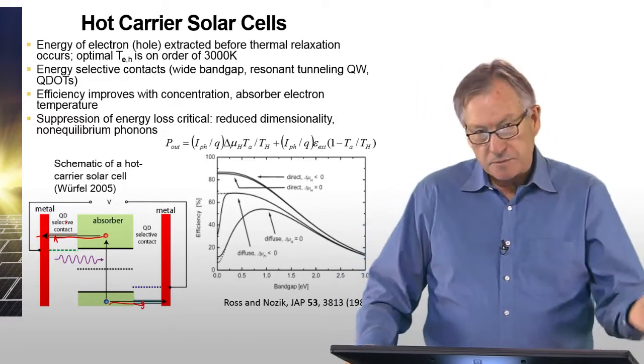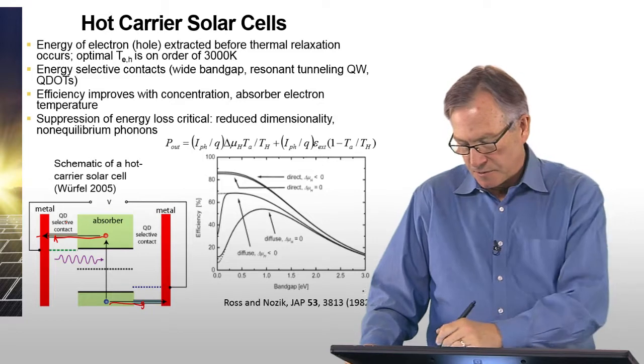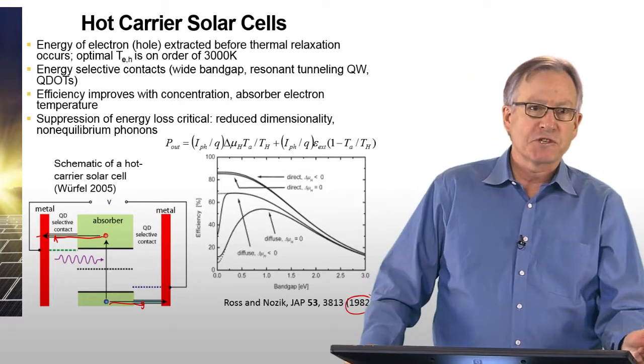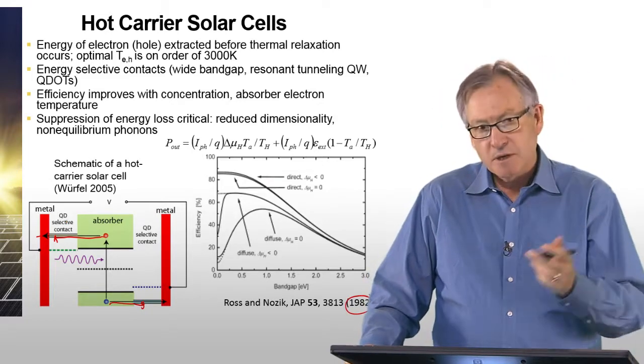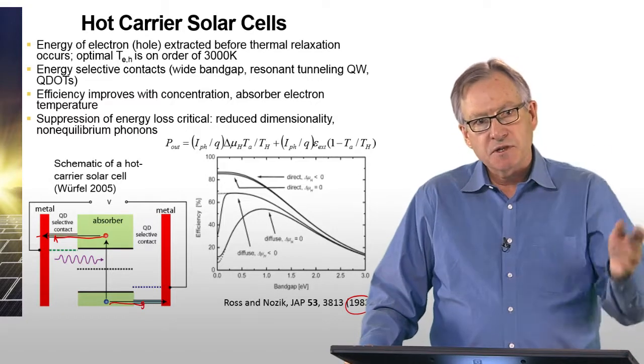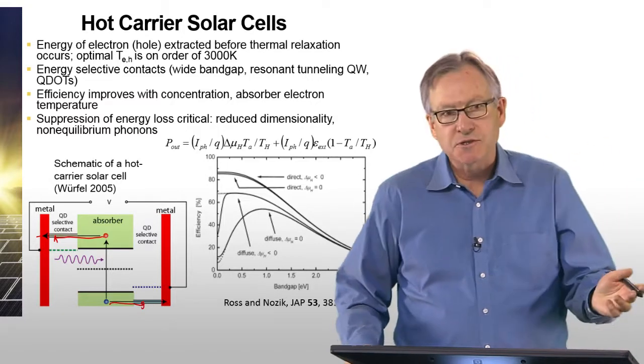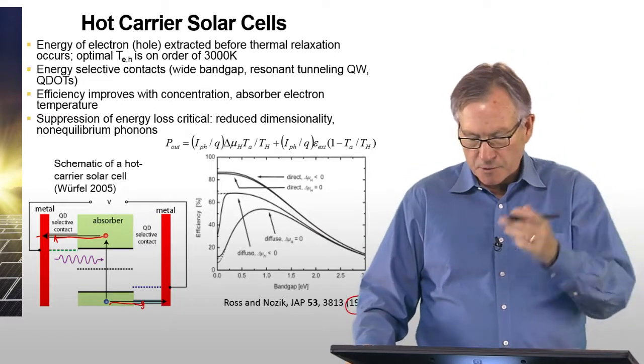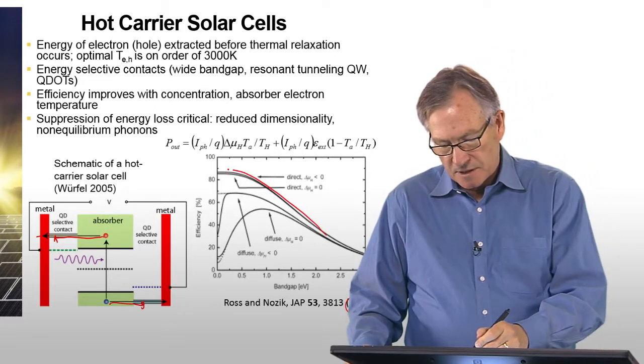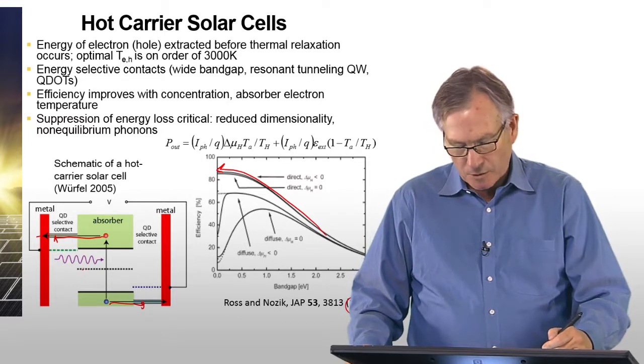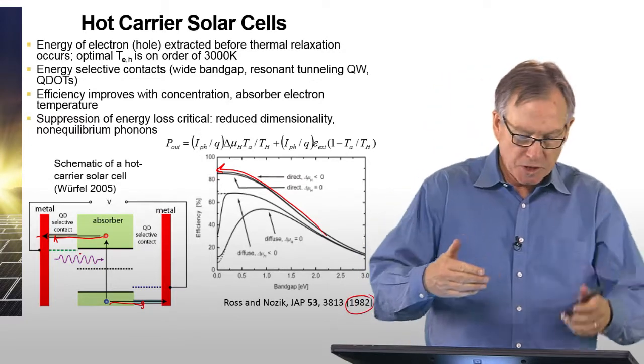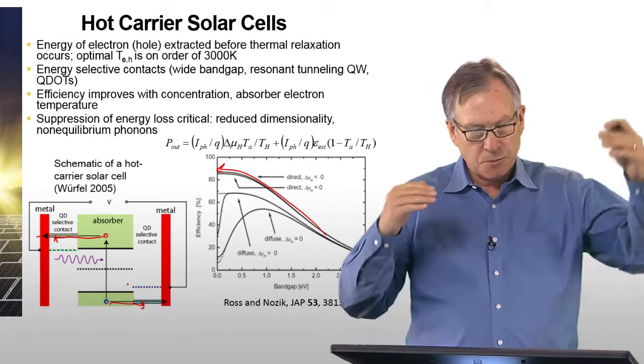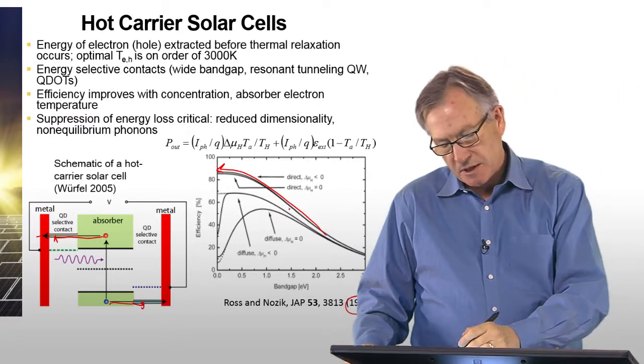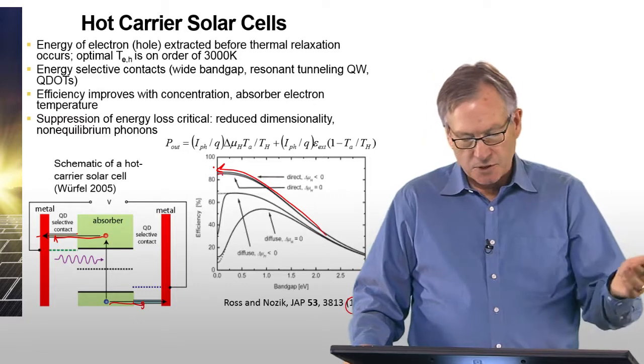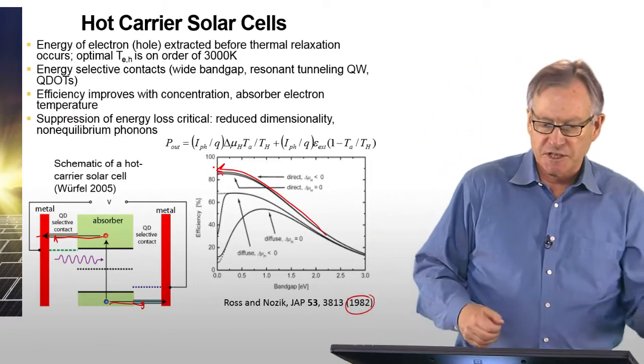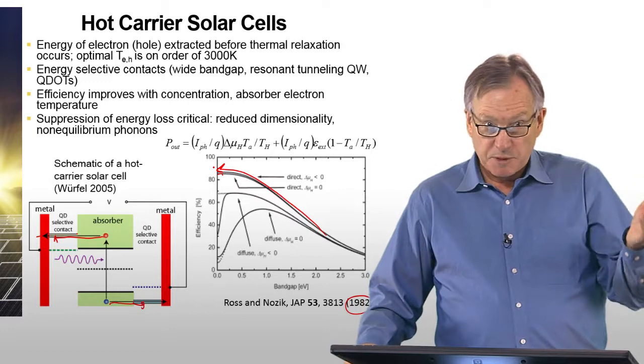This is an old concept actually, it was first proposed in 1982 by Ross and Nozik. And they used, again, this ideal detailed balance analysis to look at the maximum conversion efficiency. As you can see, as the band gap of the absorber gets smaller and smaller, you're absorbing more and more photons, but you're still collecting at an energy that's determined by the energy selective contacts. And so the theoretical efficiency goes all the way up to the maximum theoretical efficiency of 86%. That would be great if we could achieve that.